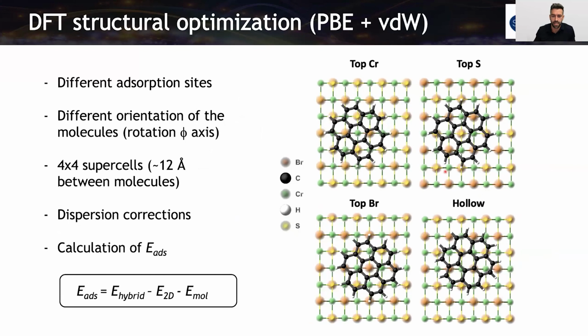To do this kind of calculation, we need to test different adsorption sites, also the orientation of the molecules using rotation along the phi axis. We have to build supercells because we want to study the effect of individual molecules in terms of hybridization and effects. Of course, then we can also model a kind of monolayer of molecules, and we always add dispersion corrections. We calculate with this formula the adsorption energy, that is the total energy, the ground state of the hybrid, and we subtract the ground state of the fully relaxed 2D material and the molecule.